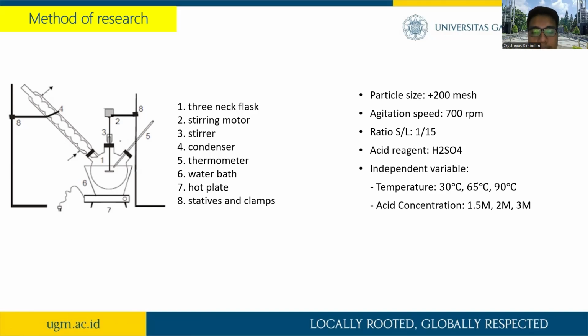Red mud samples were first dried using an oven for approximately 3 hours, adjusting the initial condition of the sample, at 105 Celsius degree to ensure that the red mud sample to be used was completely dry. After that, the dry red mud will be reduced in size using a mortar and pestle. Then the size of the red mud is made uniform to a size of up to 200 mesh using a sieve shaker.